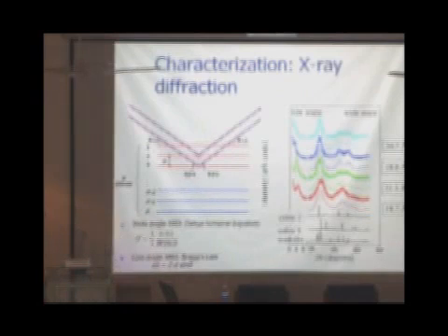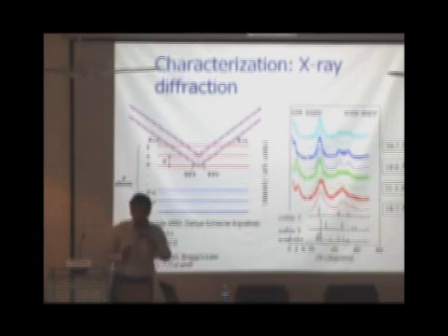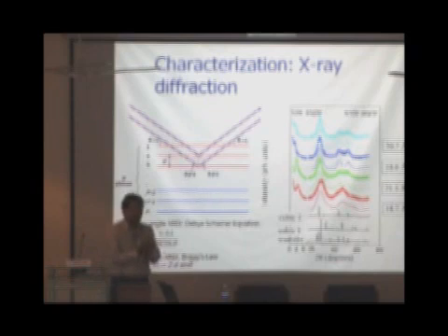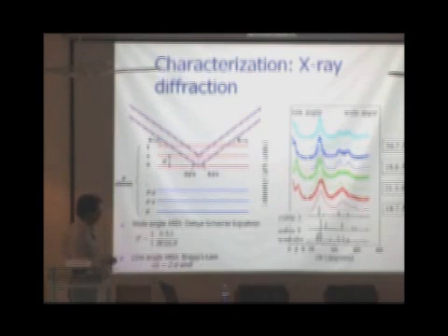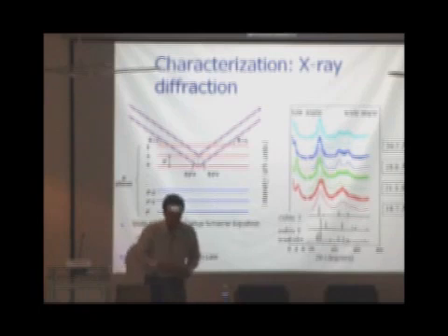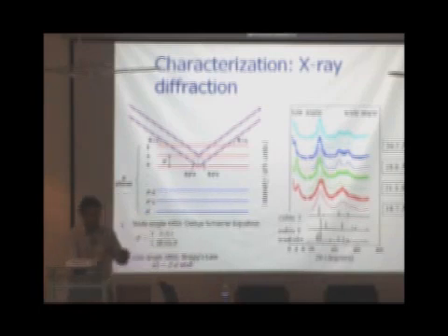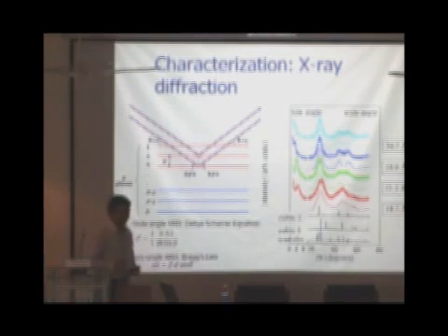When you do an X-ray diffraction experiment, there's something called the Scherrer equation, from which you can get the size of the nanoparticles, or the nanocrystals to be exact. I should be more careful using this word nanocrystals, because the X-ray diffraction size that you get is only for the crystalline part. And if Professor Mehta is angry with me one of these days, I just don't go to the TEM, I go to the X-ray diffraction and immediately get the size of the particles. But normally he's not, he's in a good mood.